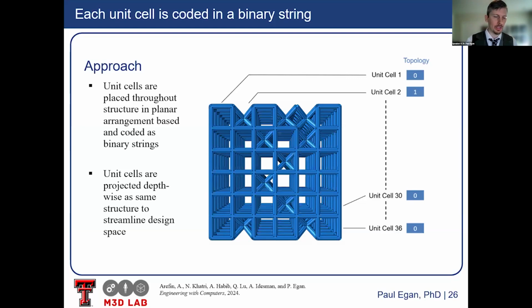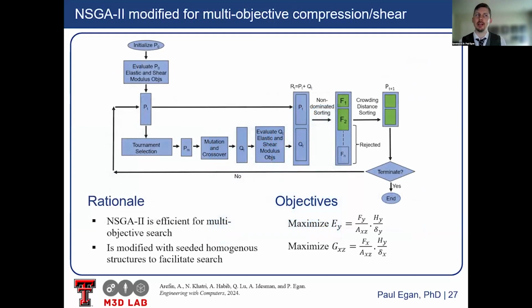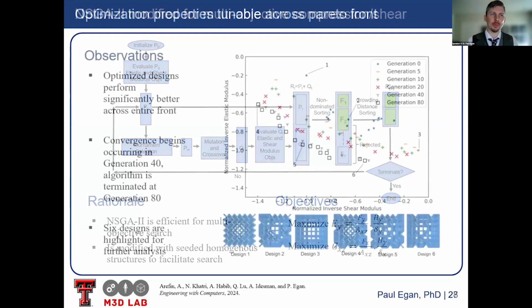And so in order to optimize this, we used NSGA2, multi-objective optimization. You can see the objective functions in the bottom right. We have that elastic modulus and the shear modulus. And so what we're going to do is create a population of unit cells and scaffolds that's randomly generated. And then we're going to start creating Pareto fronts where you have the trade-offs between the two of them, where you can't improve one parameter without compromising the other. And so from those best Pareto fronts, we're going to improve that each iteration. And so that's what you see here.